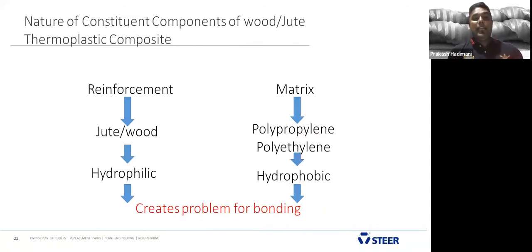Okay, natural fiber has to be mixed with the polymer now. How to do that? Because reinforcement like jute and wood powder are hydrophilic in nature, and the matrix of the polymer is again hydrophobic in nature. We need to mix these two. We need a compatibilizer as a bonding agent. And again, to mix these two, we need a twin screw extruder so that we can distribute the fiber into the polymer matrix, to get homogeneous mixing.